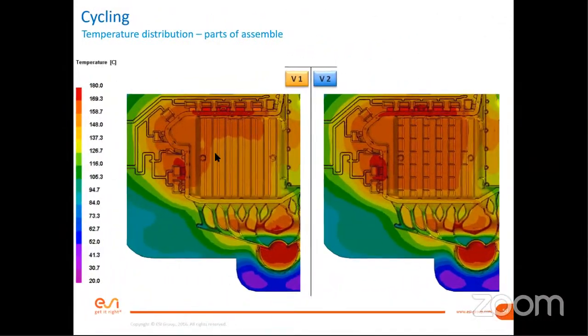Yeah, so we can see the final state of the die after some number of cycles. Each cycle brings some heat up of the die. Each cycle brings some cool down using the cooling channels, using the treatment of the surface of the die. So in the first stage of the simulation, we are looking for the steady state. If we have this steady state, we can say that we know the temperature distribution of the die, and we can continue with another simulation.